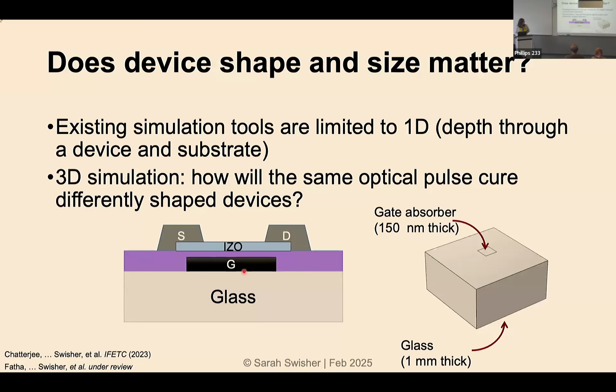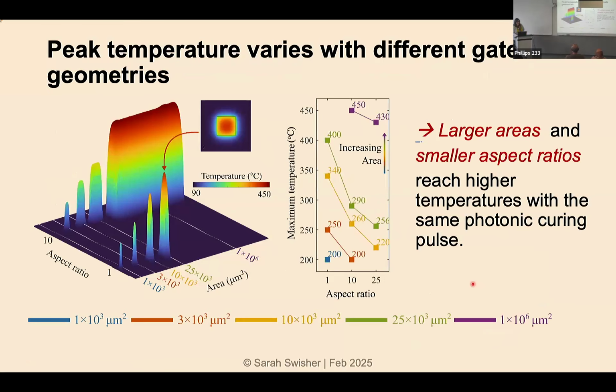So this is the cross-section of our device. Again, we've got our metal gate. Our semiconductor is going to be up here. But we're simulating the temperature that's generated here in the gate on a glass substrate. So we've got 150 nanometers of our gate metal, and we have a 1 millimeter glass substrate, and we're going to simulate this 3D volume. And what we found here was exactly what we expected.